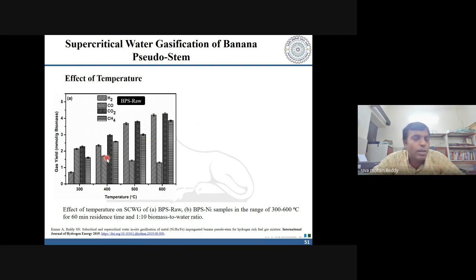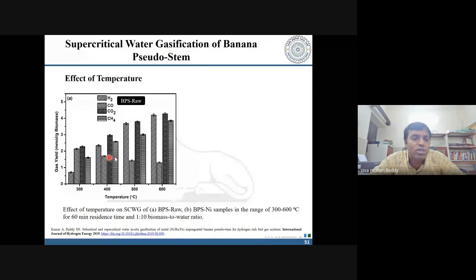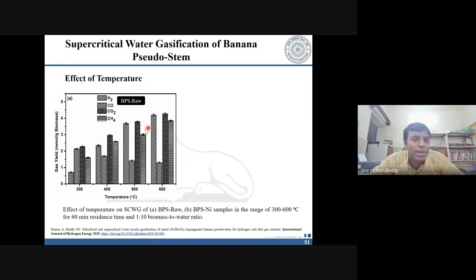Now, whenever you are going to have cracking and reforming reactions, you see that the hydrogen gas yield is going to be significantly increased. Not only that, you see that with the increase in your temperature, your carbon dioxide yield is also going to increase significantly, which conveys to us that the reforming reactions of the intermediates, not only intermediates but also the gas forms like methane and CO, undergo the water gas shift reactions to selectively enhance the hydrogen gas yields.